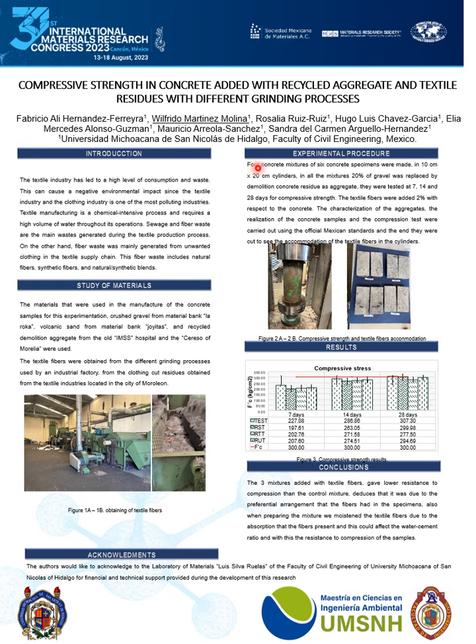We made 4 concrete mixtures, and 6 concrete specimens were made in 10 cm diameter by 20 cm height cylinders. In all the mixtures, 20% of the gravel was replaced by demolition concrete residue as aggregate, and they were tested at 7, 14, and 28 days for compressive strength. The textile fibers were added at 2% with respect to the cement of the mixture. The characterization of the aggregates, the preparation of the concrete samples, and the compression tests were carried out using the official standards, and in the end, we could see the accommodation of the textile fibers in the cylinder.